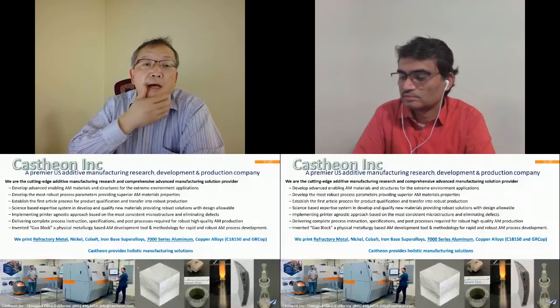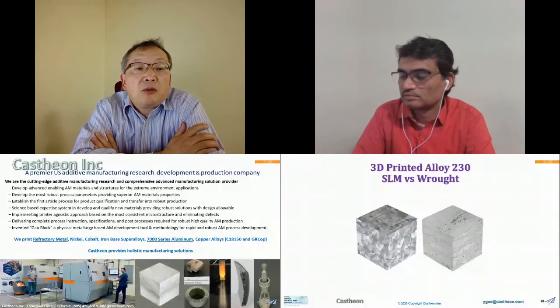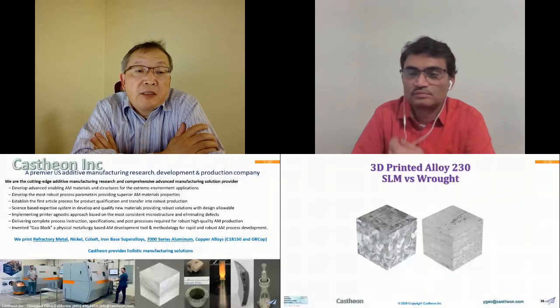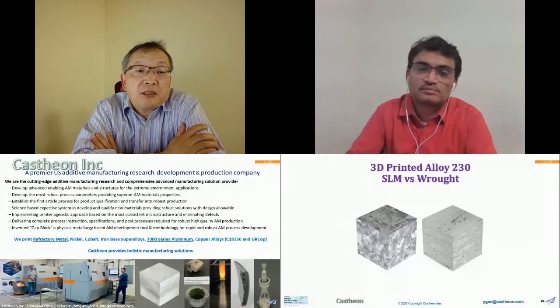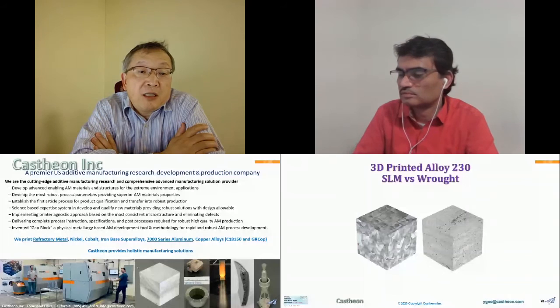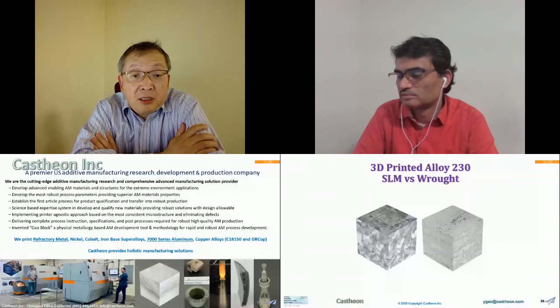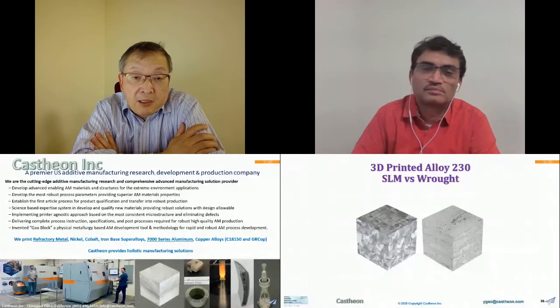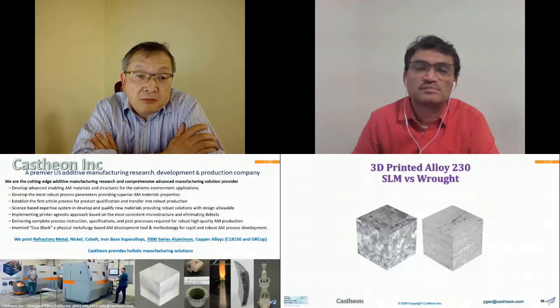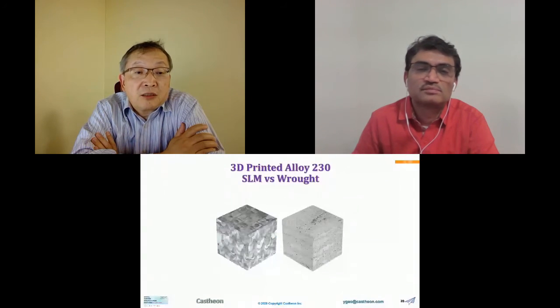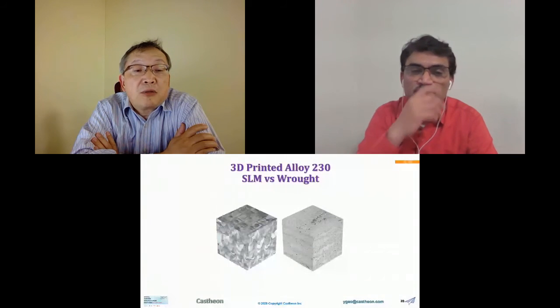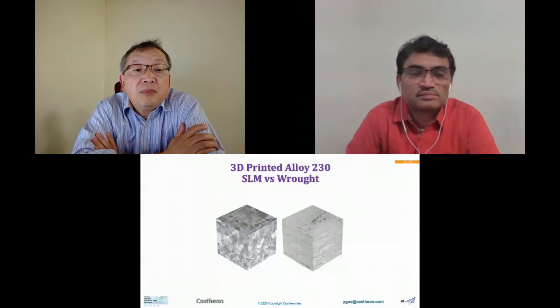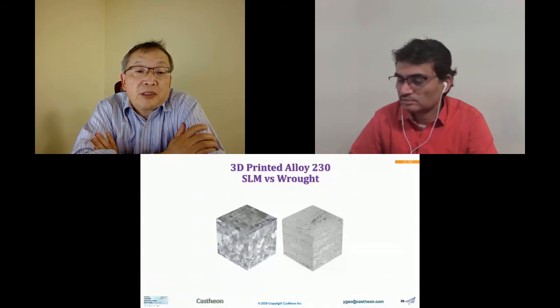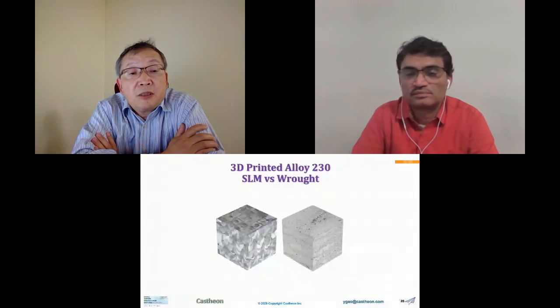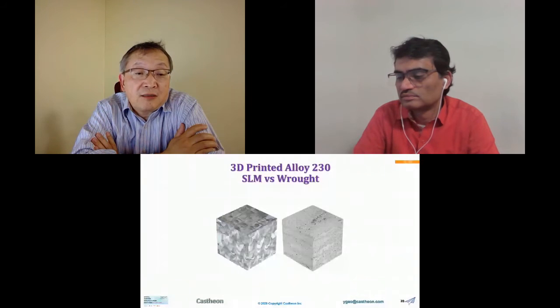All right, next one. So we're really focusing on how to optimize the grain structures of the additive manufacturing. On the chart, on the left is the additively made material, and on the right is a forged material. And you can see the additive looks awful. This is as-welded microstructure, and depending on how you etch them, you're going to see a different grain size. The grain size is typically pretty large, about ASTM grain size of 4 or 5.